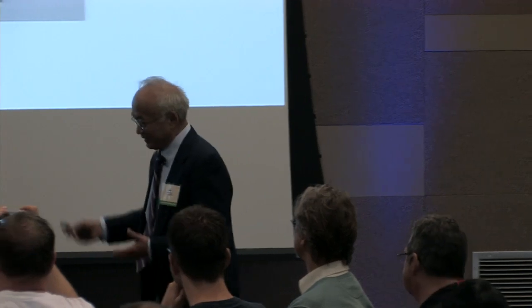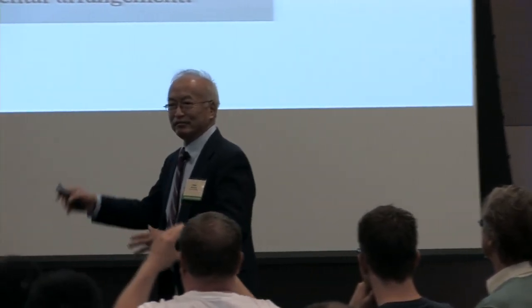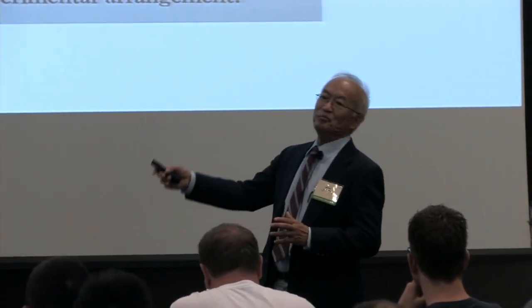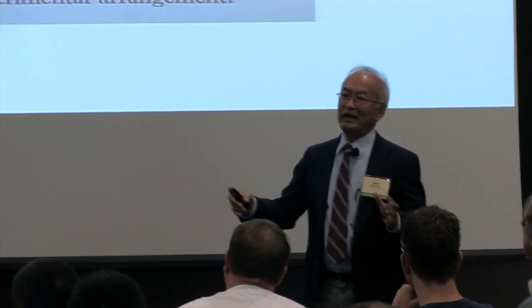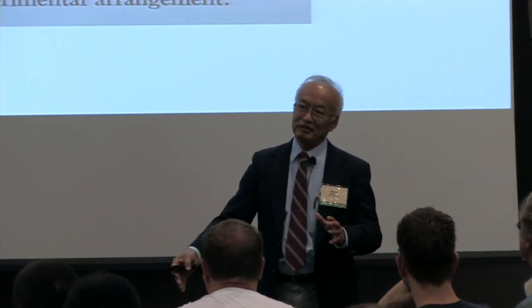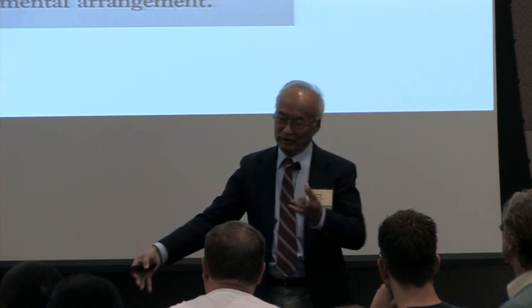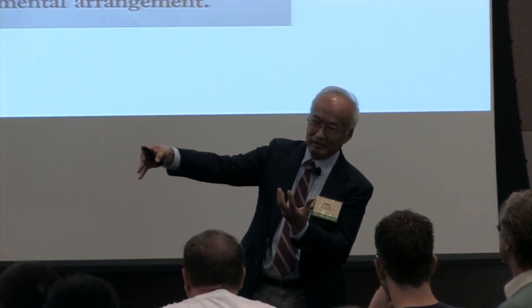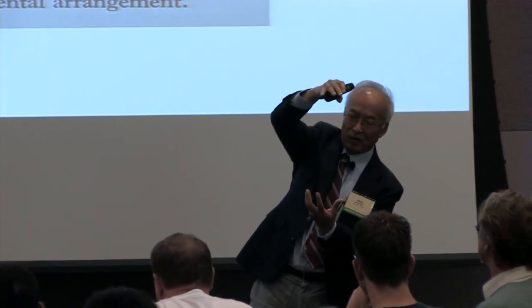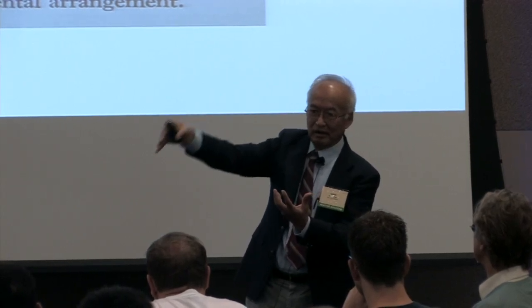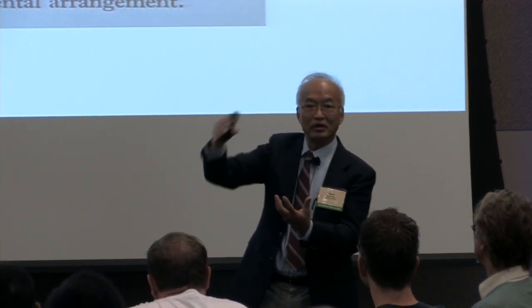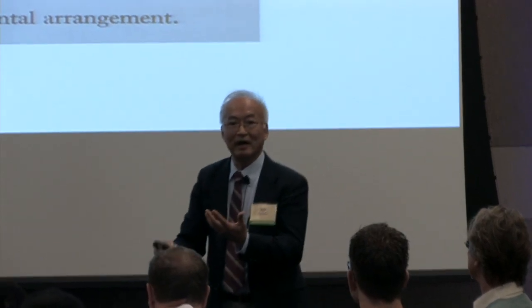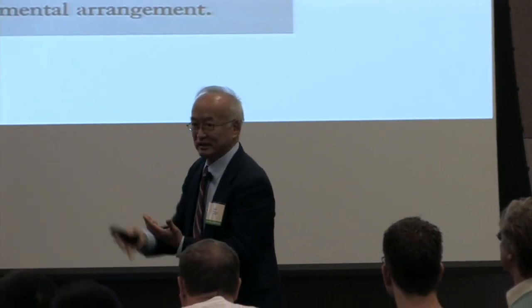So from then on, in the next generation of MBE, I lowered the diffraction guns to 5K, 10K. And of course, I'll show you why. There's a difference in the diffraction of higher energy ones. For higher energy, the Ewald sphere diameter is larger. So when you have the reciprocal rods there, you can look at higher orders of the reciprocal rods. With 10 to 5 keV, you only intersect the first order.